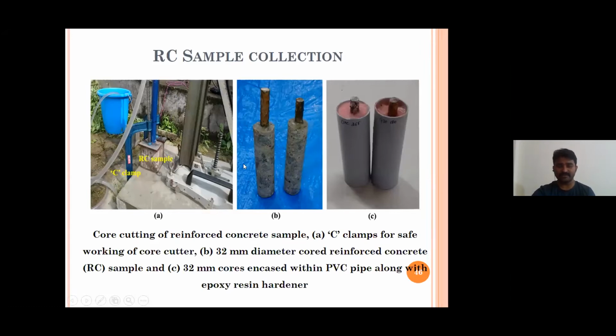This is how the steel concrete portion looks like. And after that, if you start cutting the concrete to observe the microstructure using high-speed cutters or low-speed cutters, the concrete would thrash out, or concrete would chip out, in other words. So to avoid that step, we have encased these cores in a PVC pipe, and we have added some rapid hardeners.